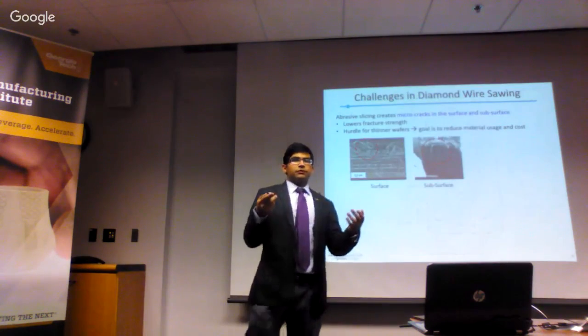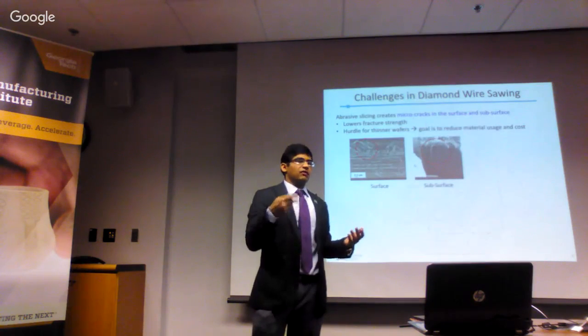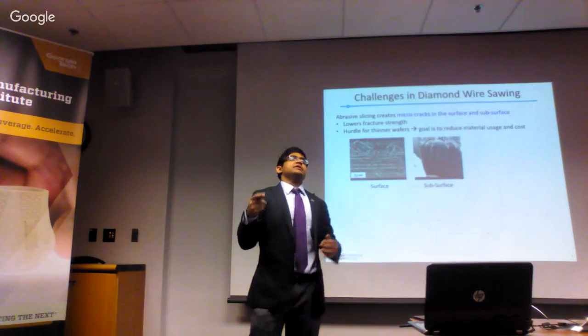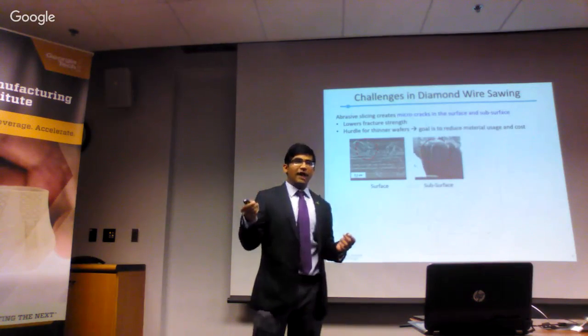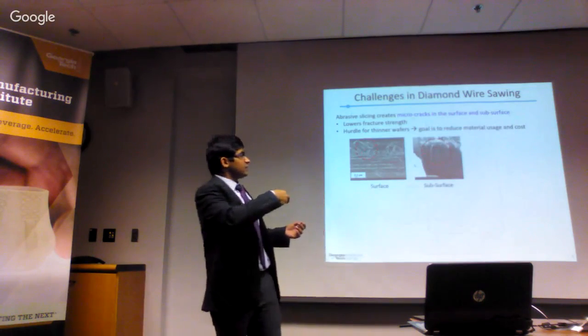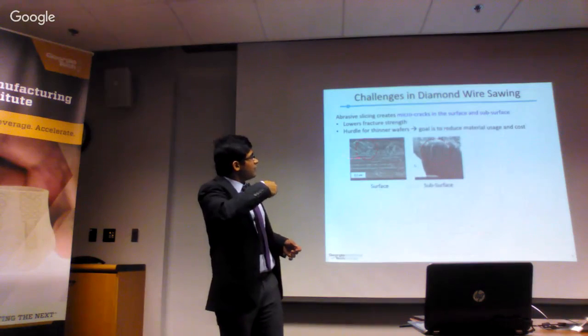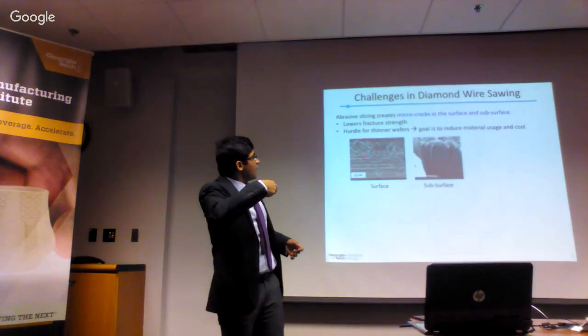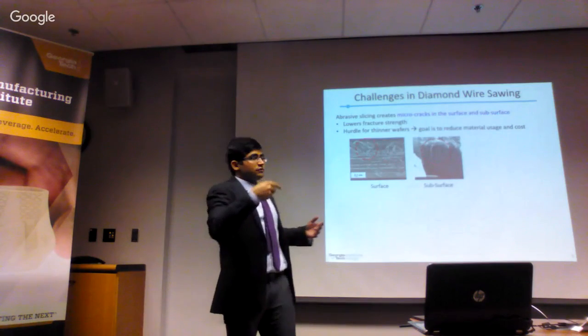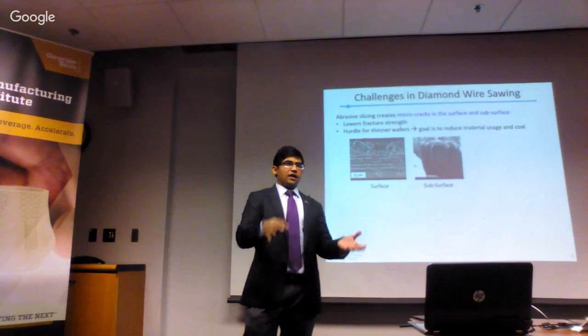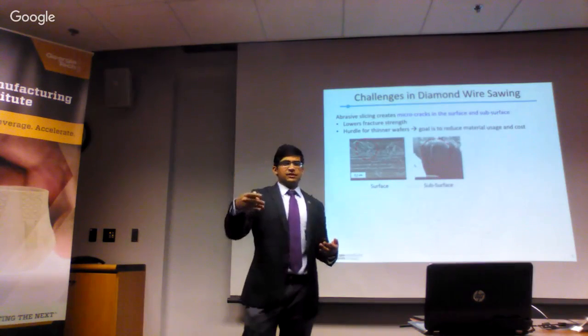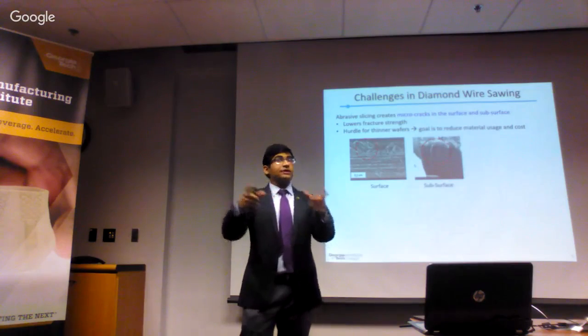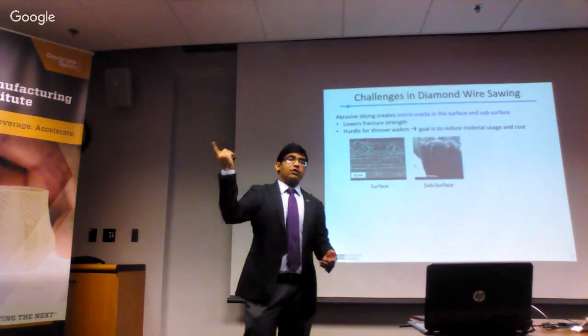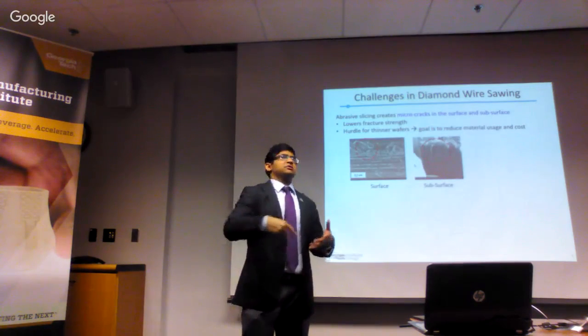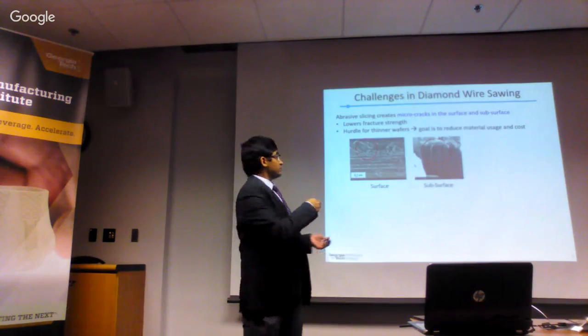Now, to look into the challenges in the current state of the art of diamond wire sawing, one of the prime challenges is the abrasive slicing process creating micro cracks in the surface and subsurface of the silicon wafers. Here you see the surface of the silicon wafers, a lot of scratch marks going from left to right, and there are these cracks, which you see here. These cracks can propagate when the silicon wafers are processed into solar cells with processes like etching to remove surface damage, then doping, handling of these wafers to make them into solar cells, putting them into modules, or even during usage. When they're on our rooftops, there's thermal expansion going on, hailstorms, etc. And these break more easily because of these micro cracks.